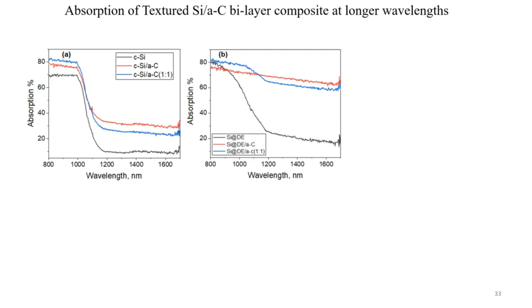And here we can see that in figure A, for the crystalline surfaces, even with the amorphous carbon overcoating, absorption decreased significantly, but for the textured silicon surfaces, absorption was quite steady, and we can attribute this to the effect of both the porous amorphous carbon coating and also the textured silicon surfaces, which come into play to improve the optical properties.